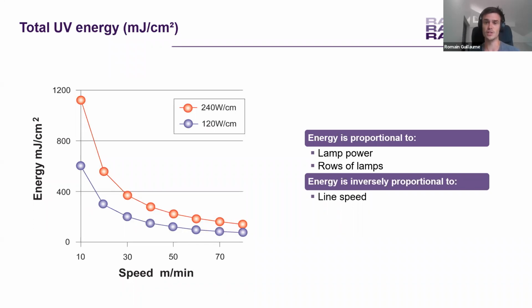And like I said previously, the energy is inversely proportional to the line speed, which is also quite easy to imagine, because if you increase your speed, you will decrease the time that the coating has below the UV, and so the total amount of photons received by your coating formulation. So that's about the UV energy, and this UV energy is something we have to take into consideration when we have to define a UV or electron beam system. With this information and the speed of the line, we already have a good idea about which power of lamp we need to use, and also the number of lamps we need to integrate into the system.